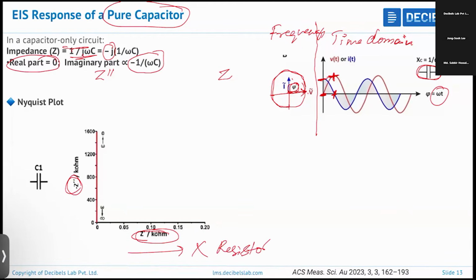So therefore, we get the impedance along the y-axis. You can see that the red one, which is parallel to the negative imaginary axis, is an electrochemical system having only a capacitor. You can see here the impedance is less when the frequency is high, because Z is inversely proportional to frequency in this case. And when frequency is 0, impedance is high.